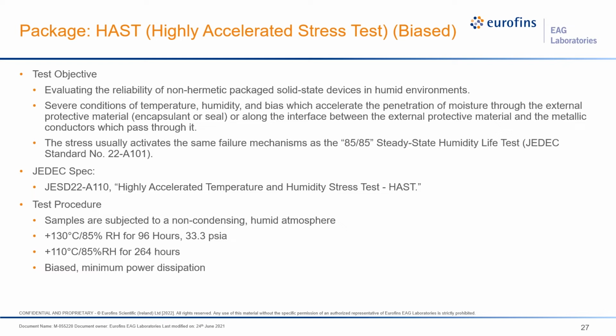Previously, the temperature humidity bias test, 85/85, was used to test for this. Due to the 1,000-hour duration of THB, it has largely been replaced with the biased HAST. There are two different temperature ranges and durations per biased HAST. The 130C, 85% relative humidity for 96 hours is recommended for leaded packages. The 110C, 85% humidity for 264 hours is recommended for ball grid array packages.